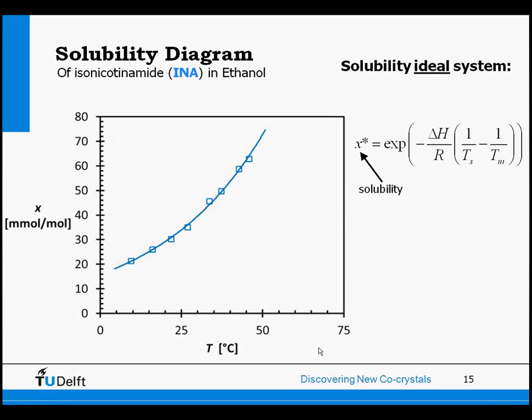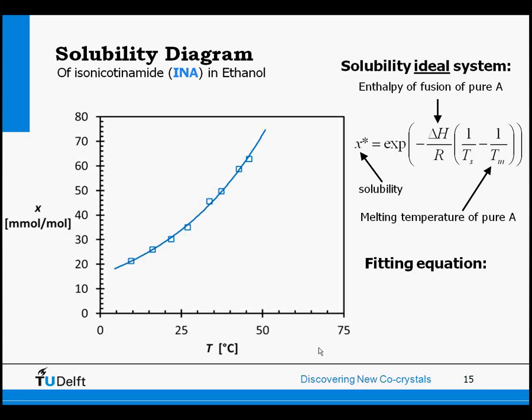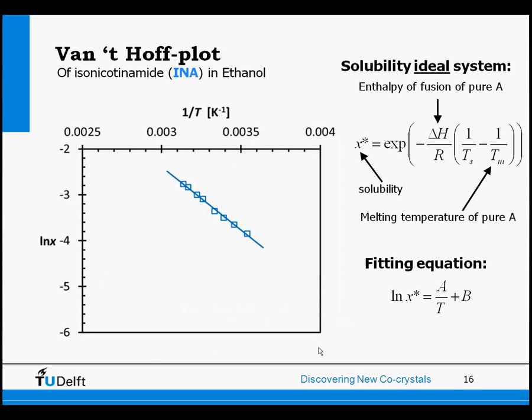You have the solubility, which is marked as x star, so mole fraction, here millimoles per mole. And that's described as a function of the enthalpy of fusion of the pure component, so in this case isonicotinamide, and the melting temperature of the pure component. This is a theoretical description, but we can use a fitting equation with which you have two parameters to fit the line to, and we can do that in a van 't Hoff plot. So then you plot the log of x versus 1 over the temperature in Kelvin this time, and if all is well, you get a straight line, and that can be fitted with this equation, and you can determine A and B, and then you can extrapolate and interpolate the solubility data.